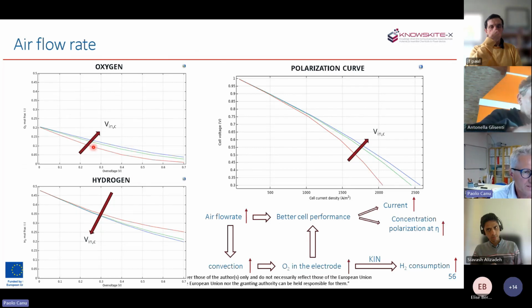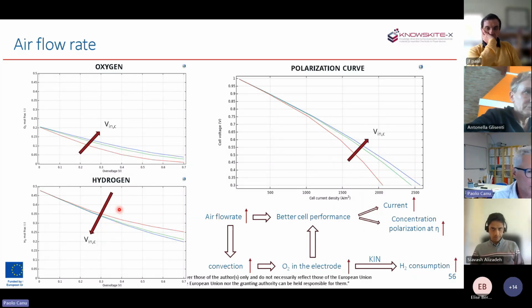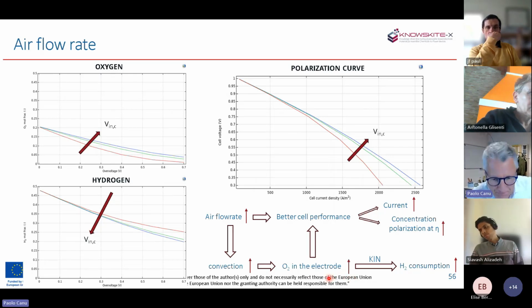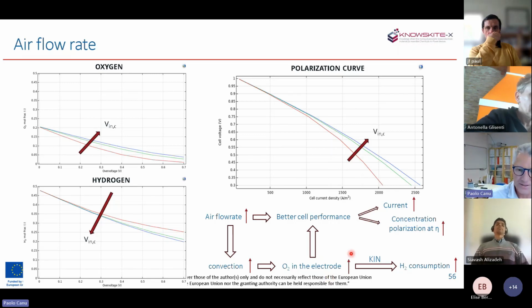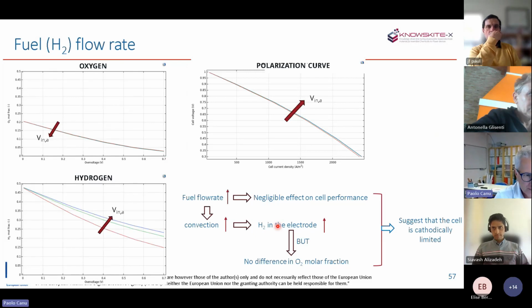That's the effect of increasing the amount of air fed on the cathode side. And we see that the consumption of oxygen is increasing. And as a side effect, also the consumption of hydrogen is increasing, mainly because a higher flow rate of oxygen in the cathode compartment increases the convection. That means more oxygen reaches the electrode, supporting a higher activity of the electrode. That means a higher current, so a higher consumption of both oxygen on the cathode and hydrogen on the anode. Let me skip a few.